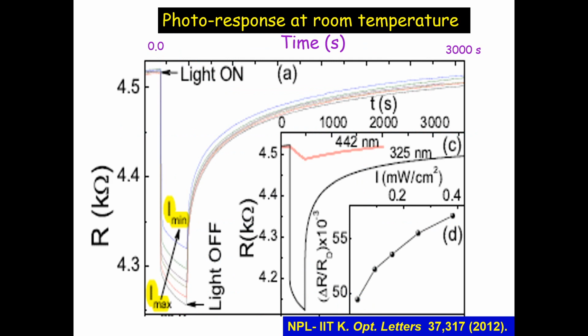The second one was shining light on it. And this, again, we did it for the first time. You shine light on the channel, and it turns out that the moment you open the light shutter, this was a white light source from a quartz halogen lamp, you see that there is a large drop in resistivity, and it remains conducting.